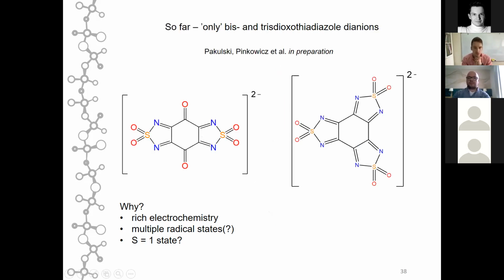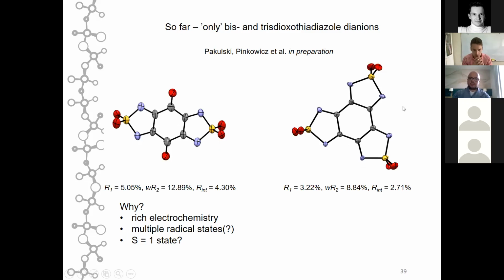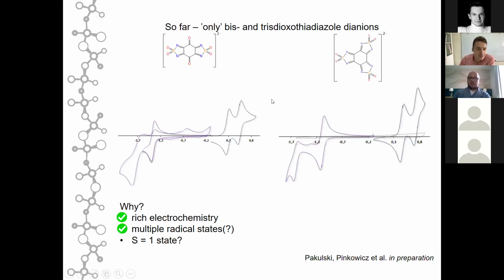So what we have actually obtained and characterized are these two types of dioxothiadiazoles. What is interesting about these molecules is that they don't contain any hydrogen atoms, only heavy atoms, not lighter than carbon. We have characterized them structurally, and they are both obtained in the form of dianions. And here is the electrochemistry for both compounds.